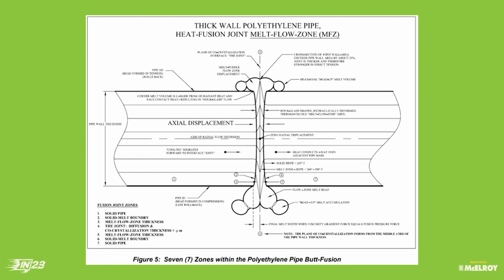Yeah, but we're with the guided side bend test up in the Marcellus. We're telling our customers and contractors to use the guided side bend test for large diameter, but they're still using, and I know Jim, we've talked, they're still using the McElroy infield tensile testers, testing at 12, 3, 6, and 9 on the pipe. One could be a perfect joint, all four pass. Another one, perfect analog joint, one will fail. Then they're looking at pipe, they're calling us.